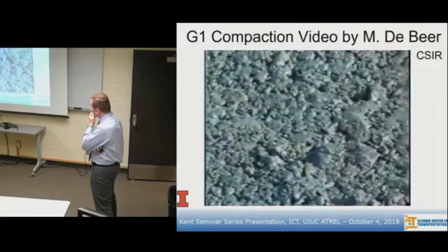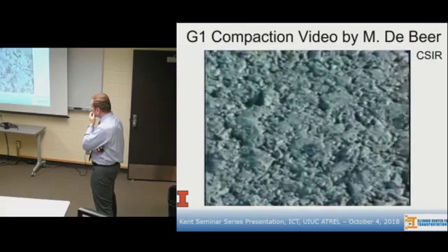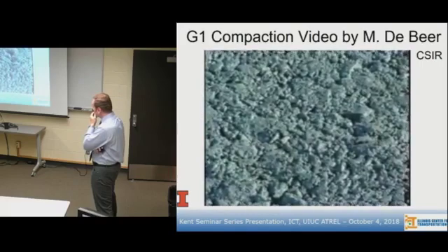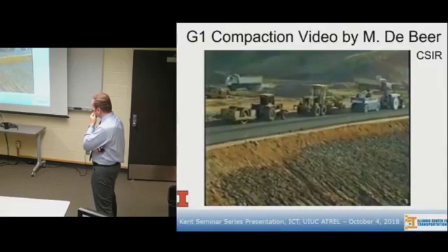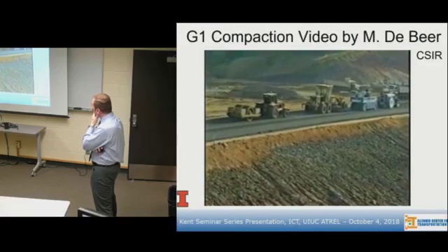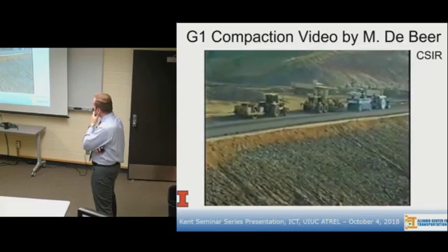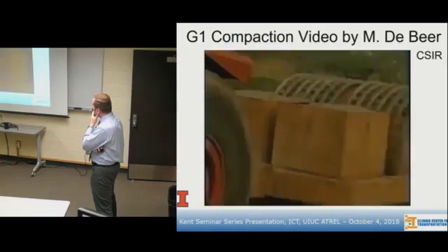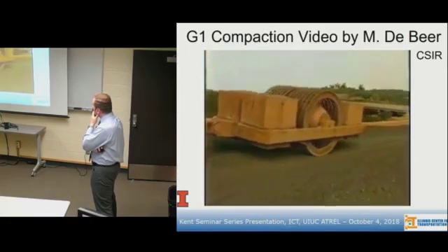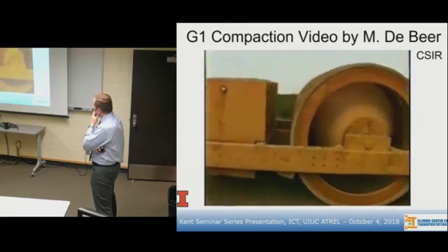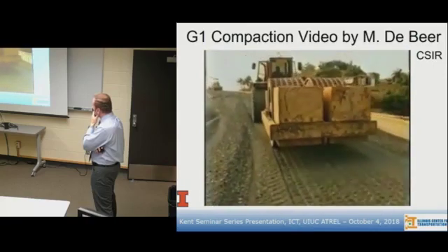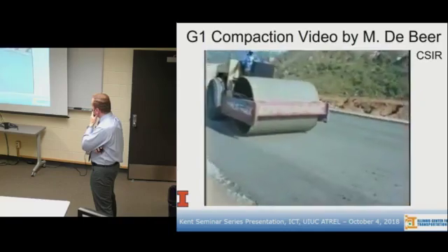The material should be at optimum compaction moisture content, ensuring that the matrix can be normally compacted to the minimum first phase density requirement. While some deviations to the basic approach to G1 compaction have evolved over the years, mainly being the solutions to variations in material quality, available equipment and local conditions, the original method will be described here. To start the compaction process, layer shaping is initiated by using a grid roller for 2 or 3 passes at a slow speed to gently knead the material into position without altering the gradation.